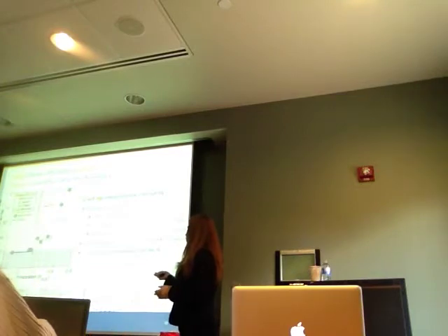Knowing the potential and pH of the cracked tip, you can get the overpotential for hydrogen production. And this overpotential for hydrogen production is very important because this establishes the concentration of hydrogen at the surface of your cracked tip. Using this relationship and a stress term, we can figure out what the concentration of hydrogen is at the fracture process zone. So that can go right into our model equation.